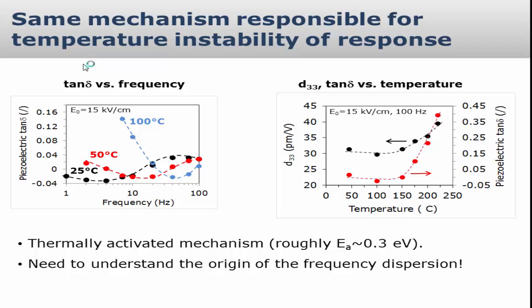The same mechanism, this broad frequency dispersion at low frequency, is also responsible for the temperature instability of the piezoelectric response in BiFeO3. So what basically happens is that this frequency dispersion relaxation shifts up with increasing temperature. And if you work, for example, at 100 Hertz, and you try to measure the response, at a certain point this D33 tangent delta, the piezoelectric phase angle, will just increase because of this shift of the relaxation to higher frequencies with temperature. So, of course, we don't want this instability, and that's one of the reasons I think that one should go into more detail to see where this effect is coming from, why this happens.